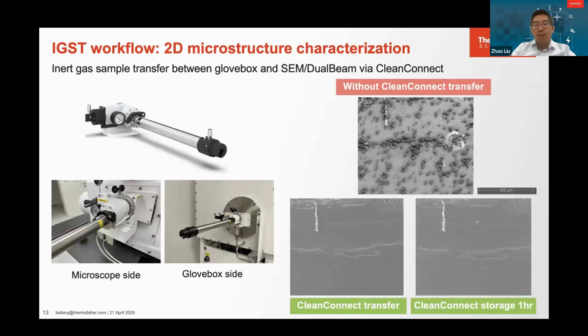And the bottom left shows that if you do the Clean Connect transfer, your sample still has a very pristine and clean surface. More than that, sometimes you need to store samples in the transfer unit, for example from your lab all the way to your microscope room, which takes some time during the transfer period. In this case, we stored the sample in the Clean Connect for over 1 hour, and you can still find that the sample is well maintained. That means under the positive argon environment, the sample integrity is well maintained.